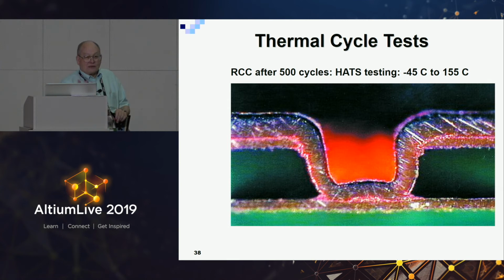But a lot of times I pay for a test to failure, so I actually know what the failure numbers are. And a lot of times I get HDI stuff back that said, we can't test to failure. We did a model that indicates this will fail after 7,200 cycles. So I'll take the model approach. You did 4,000 real and extended the model to 7,000 kind of thing. But if they're done right, they're really, really robust.